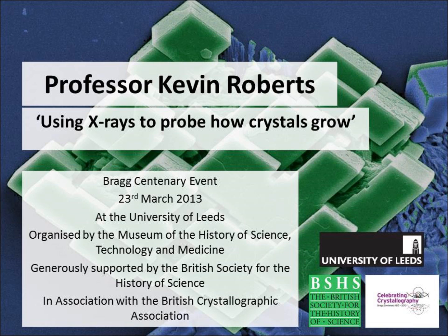And so this is our crystal, this is our cut through it, and then we have a look at all these surfaces. And we can see that if we have these dislocations coming in, they'll make steps, and the steps will make spirals. And this was Charles Frank's great discovery. And we can see these. These are atomic force microscopes. This is the protein lysozyme, which is beautiful spirals at low driving forces. And then when we go to high driving forces, we get this mechanism. So looking at the surfaces, we can get the mechanisms by which they grow, which as an engineer means I can predict how fast it will grow, which means if I'm designing a process, I can make chemical materials much more efficiently. So let's have some pictures.